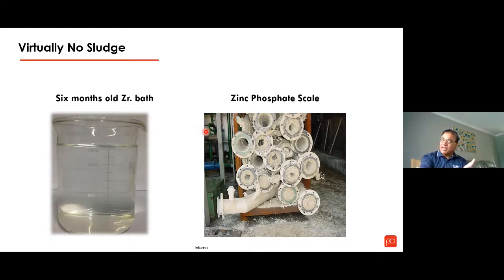Whereas with no or virtually no sludge, you would only decant the tank once every 6 months and just pressure rinse it. And you can put the zirconium bath back into the tank, optimize the solution parameters, zirconium levels, the acid levels, and all this, and you are back in business.